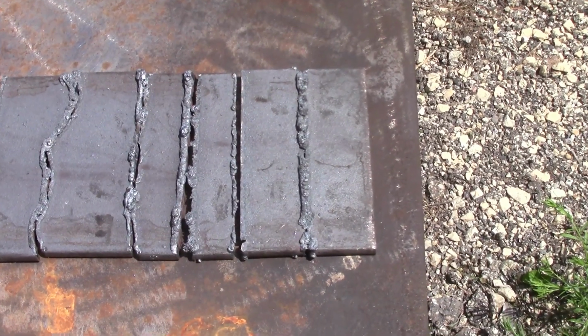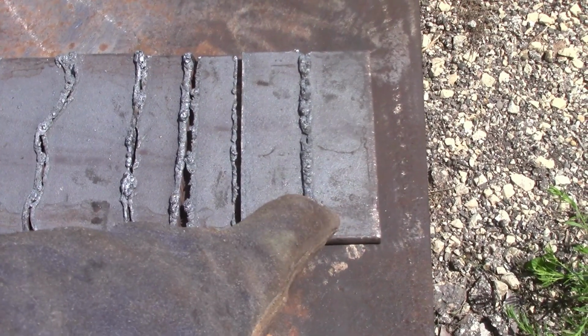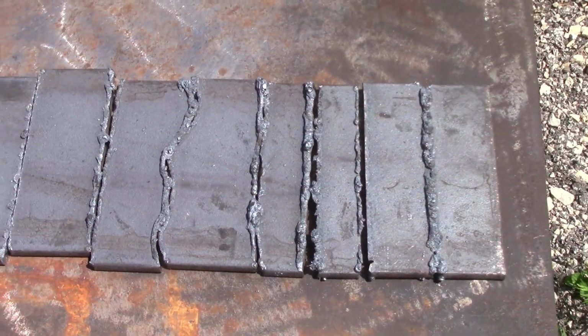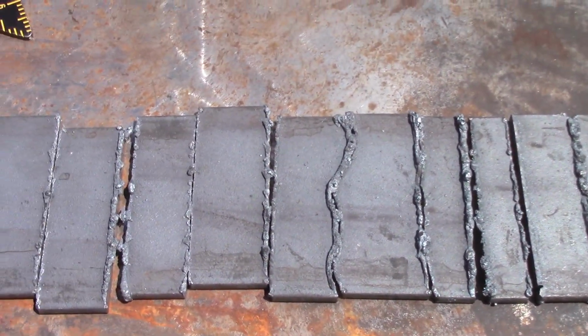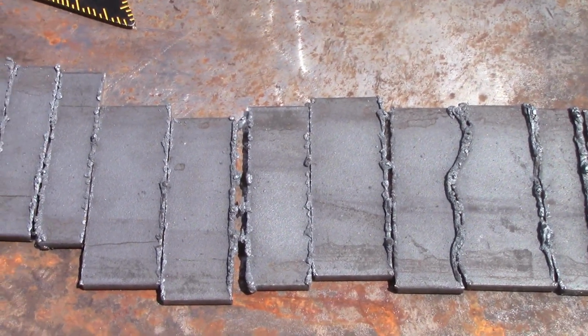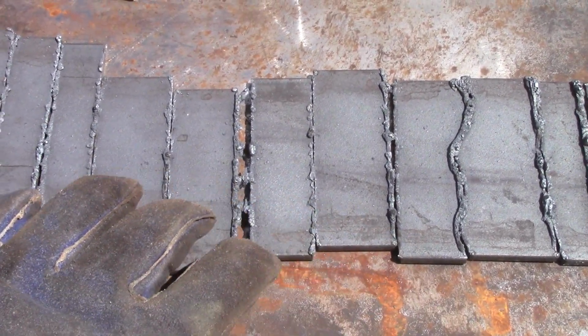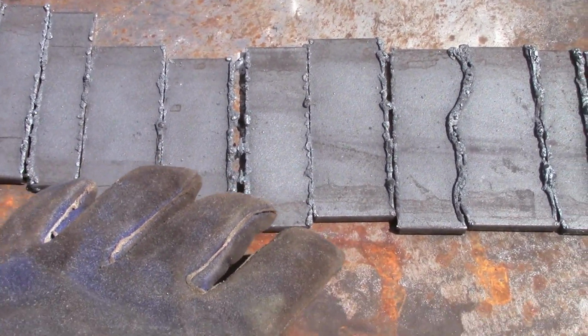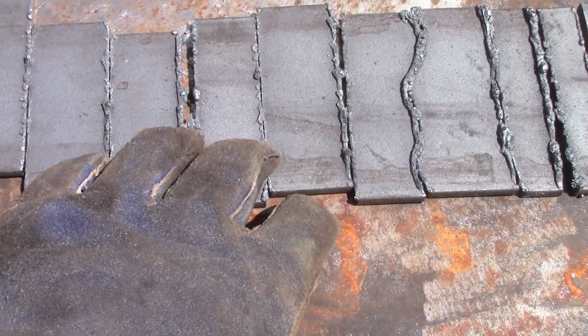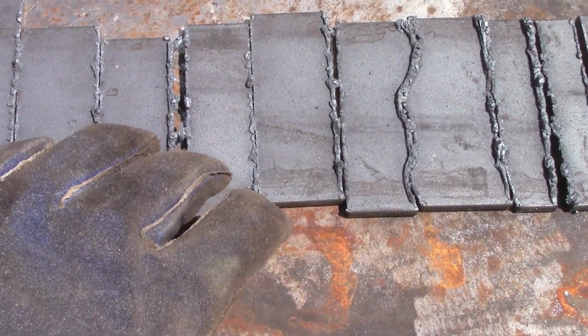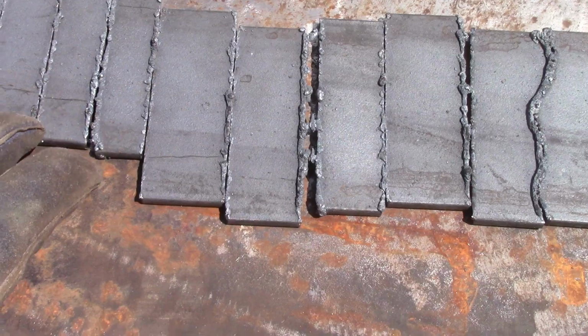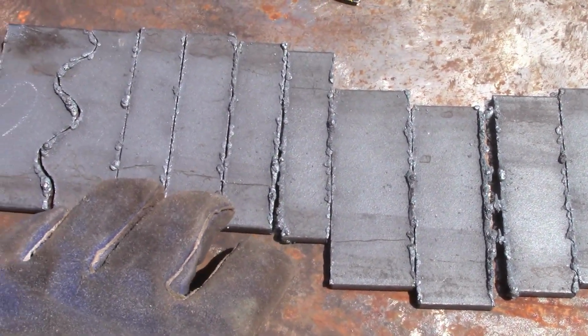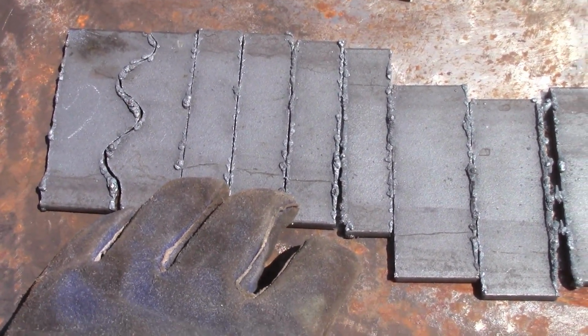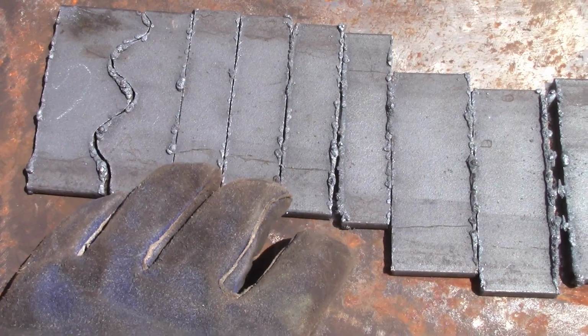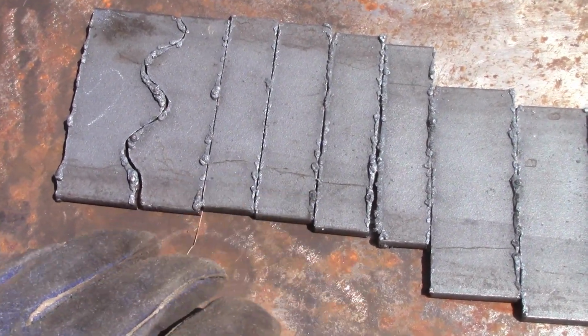Okay, so here's the very beginning of our cut, and this is where it didn't cut all the way through. And I made 15 or so cuts along here. I changed several times in between here. Starting right around here, I started messing with the pressure and the amperage. And I found my best results down here. Let's see, I was at 45 amps and 50 psi on the pressure.